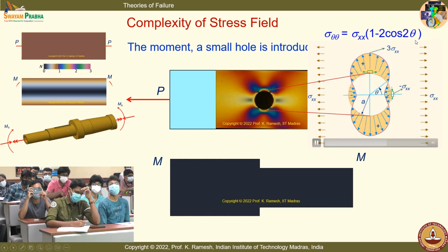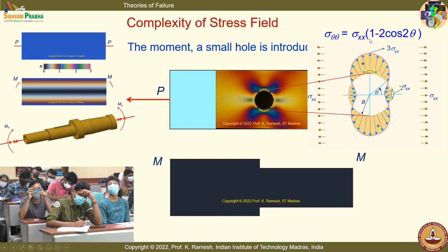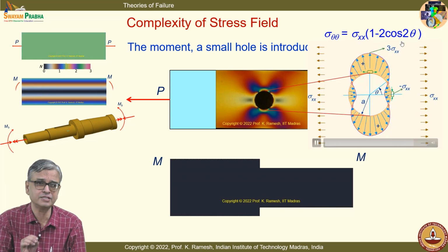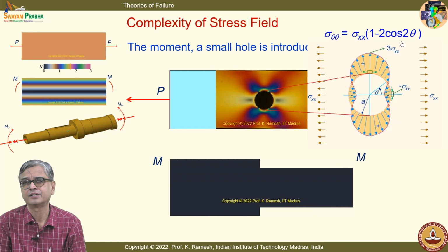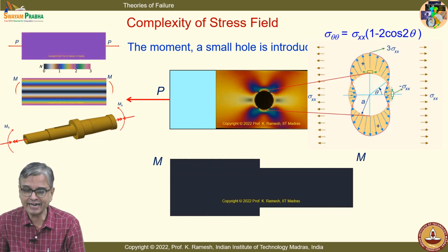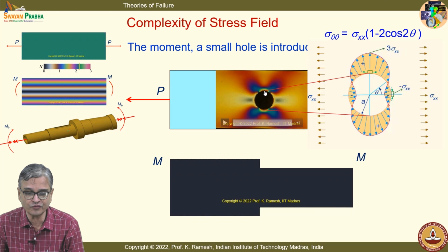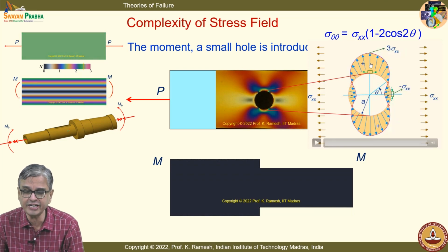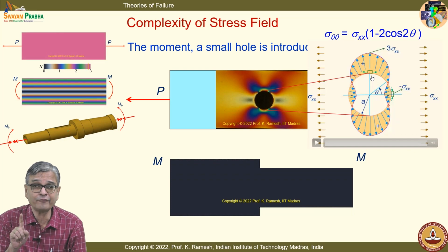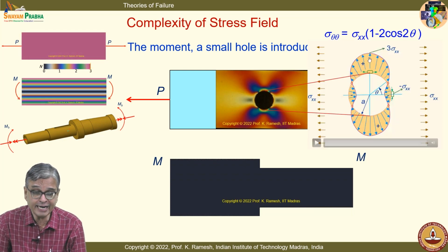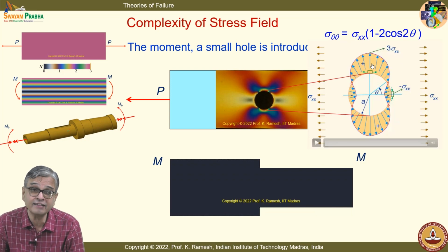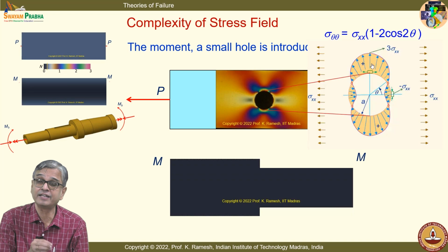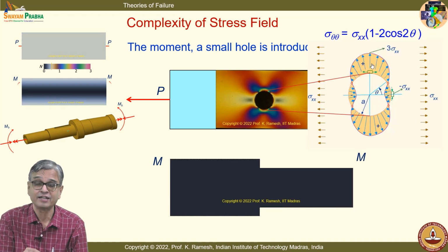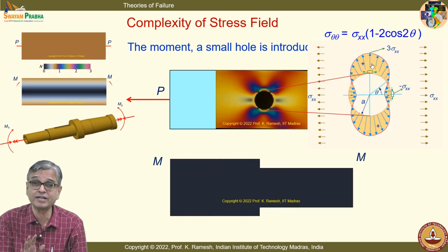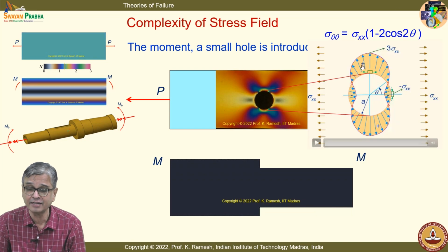I want you to write this: sigma theta theta equals sigma xx times (1 minus 2 cos 2 theta). This is a very, very important piece of information. And what I get is, where the density of fringes is very high, I get 3 times the stress. Mind you, it is for an infinite plate with a small hole. For a finite plate, it can be much higher than 3. It can even be 9 times. So you will always have to do an experimental analysis or a numerical analysis to get this stress concentration factor for a finite plate.